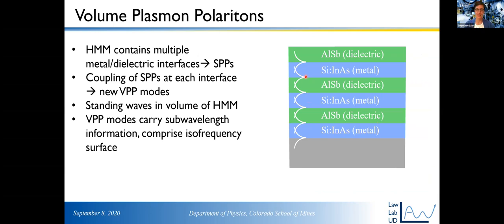They're very, very thin. In fact, they're so thin that the exponential decay of the surface plasmon at this interface interacts with the exponential decay of the surface plasmon at this interface. These two surface plasmons can couple to each other, and to this one, and to this one, throughout the entire volume of this metamaterial. So instead of just having, for example, two harmonic oscillators that couple and give you two new modes, now you have however many layers that you have. So you have lots and lots of these surface plasmon polaritons coupling together to give you these new modes.